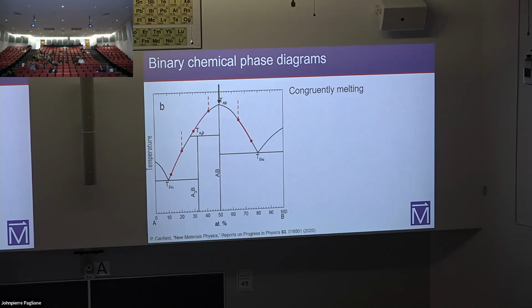In a way, this is the absolute easiest type of material to grow, except that in practice, you're probably going to run into some limitations. I'll return to this a little more later, but let me just say, what if this melting temperature is way above a temperature you can reach in your furnace? That's a problem. What if one of these elements has a high vapor pressure? That's a problem. So just because it's the simplest feature in the phase diagram doesn't necessarily mean it's the simplest thing to actually grow.